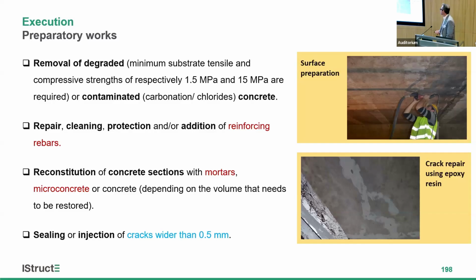And then in many cases, we have to add concrete sections using mortar, microconcrete, or concrete, depending on the level of needs in terms of volume. Finally, typically we also have cracks in existing structures, and if the cracks are wider than 0.5 millimeters, it is always suggested to seal or inject these cracks prior to the application of the system.